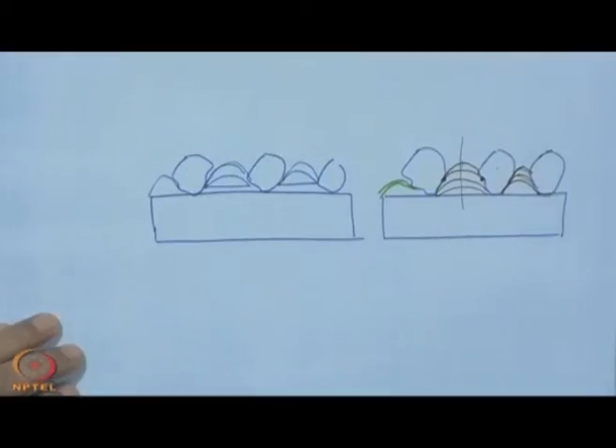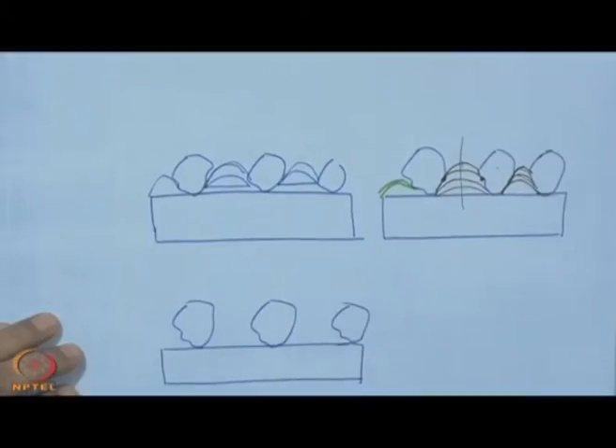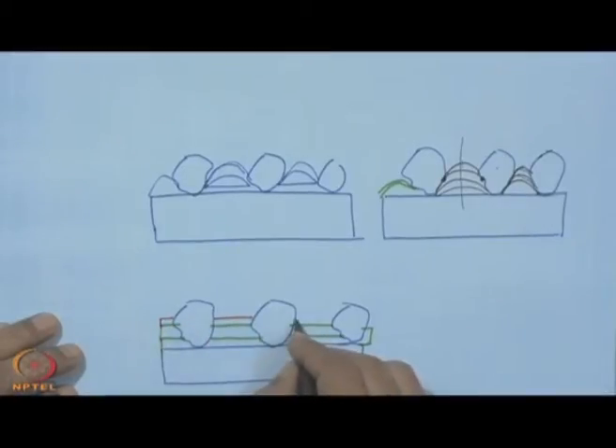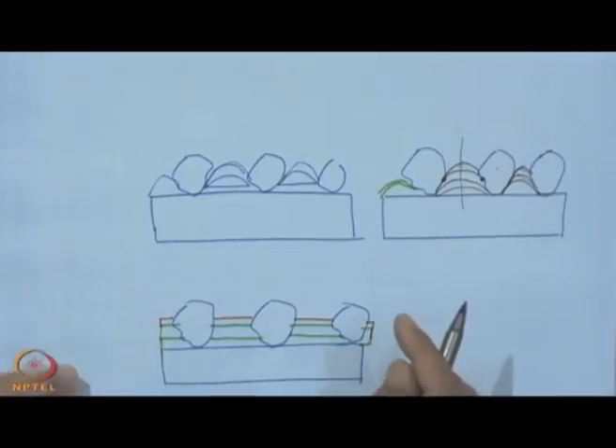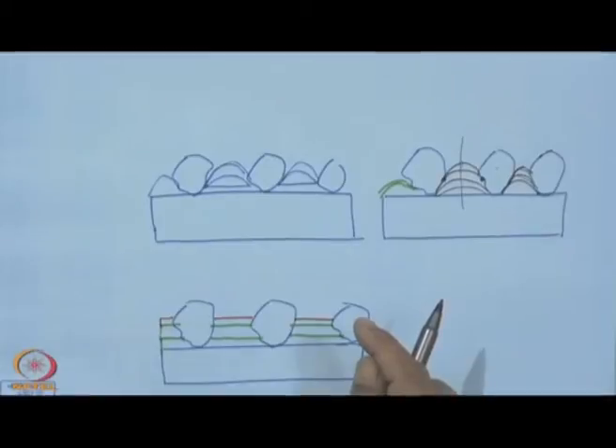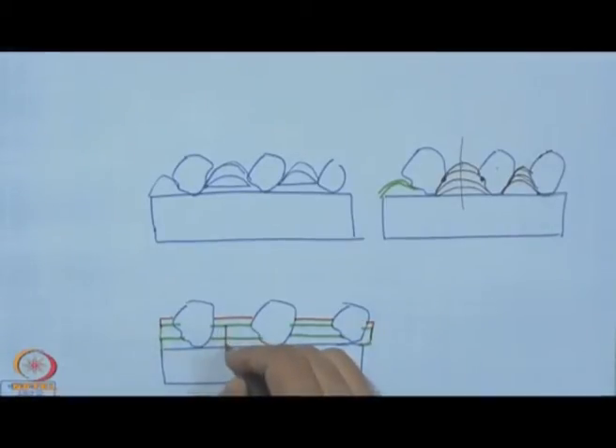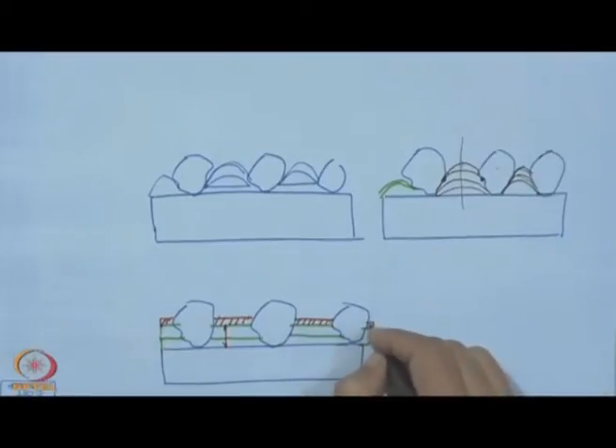Now, here what we can do, normally what we see is that nickel is used as the plating material. So, here we have the grit, and this is the plateable material. The nickel is known for its plateability. So, this way we can have the nickel build up after this tack down, but there can be another secondary coating, that means it is a multi layer, with a material, say for example chromium, which is much more oxidation resistant, and its wear resistance is higher than that of nickel. So, this layer will be nickel followed by a layer of chromium or another material which has good plateability, that can also become a material of choice.